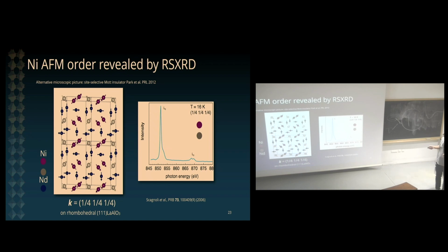That can be revealed by using resonant soft X-ray scattering. So that's an additional technique to the ones discussed yesterday for probing antiferromagnetism. That's a technique that you can only do at large-scale facilities at the moment. So you come in with a photon energy that is resonant with either an L2 or L3 transition, and then you have a scattering chamber, and you put your detector at the quarter reflection, and at the right photon energies, you're going to see some sharp peaks. So these peaks can be shown to be purely magnetic in origin. So this is really a probe of antiferromagnetism using this high energy light.